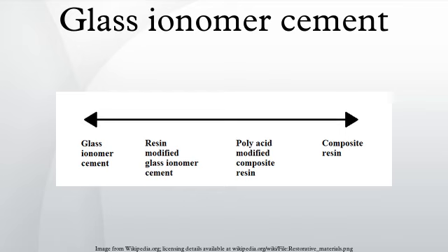As pit and fissure sealants, another suggested use of glass ionomer cements is as fissure sealants. The material is mixed to a more fluid consistency to allow flow into the depths of the pits and fissures of the posterior teeth. Early cements were found to be unsuitable for use as sealants if the fissures were less than 100 micrometers wide. The large glass particles of the cement prevented adequate penetration of fissures with a burr. A systematic review of clinical trials identified no difference between the caries preventive effects of GIC and resin-based fissure sealants.